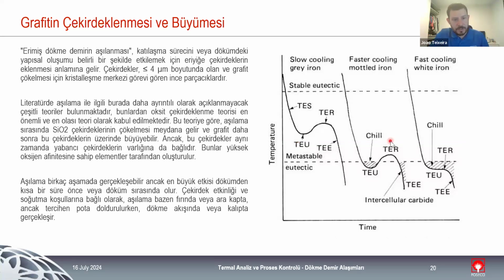Normally, when you have problems with carbides, it is because the inoculation step was not enough, and we still have a lot of carbon free in the melt at lower temperatures. So if we are lower than the metastable temperature, again around 1125, 1120, if we still have a lot of free carbon in the melt, the carbon will start to grab all the elements that are in the melt. So chromium, boron, molybdenum, all the elements that carbon has a lot of affinity with, carbon will grab all those elements in the melt and it will form carbides.